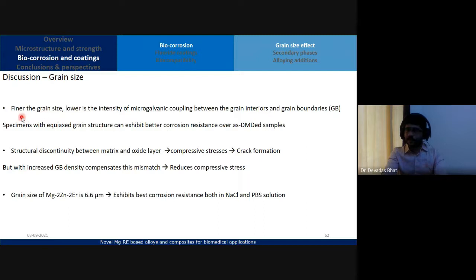Yeah, so if your grain size is finer, then, like I said before, there will be more barriers for the corrosion to take place, and we could see that extrusion gave you a better corrosion resistance than the as-DM samples. Now the oxide layer here may start developing cracks because of the compressive stress with the matrix, and this can arise because you have two different crystal structures. MgO will have a different crystal structure, magnesium will have a different crystal structure, right? But if you have more grain boundaries, that could help in compensating this mismatch in the two crystal structures, and it can reduce the compressive stress.